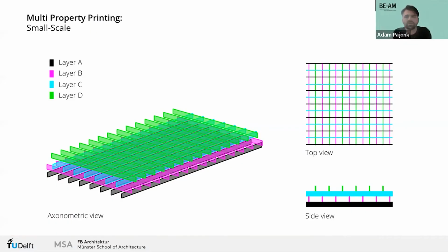Now, another way to look at this is to first define a lattice structure, and then apply these different material properties on a small scale to this predefined structure. Now, what we first did was look for a suitable structure. The structure itself has to be designed in a way that allows not only movement in the horizontal direction, but also in the vertical. Therefore, we had to introduce this shift between these layers.